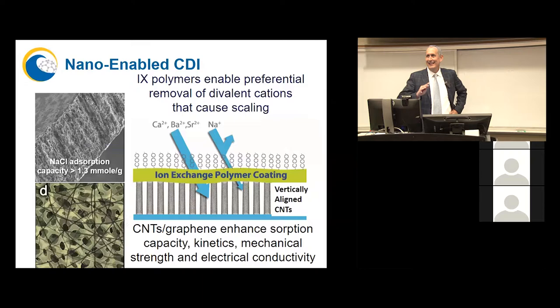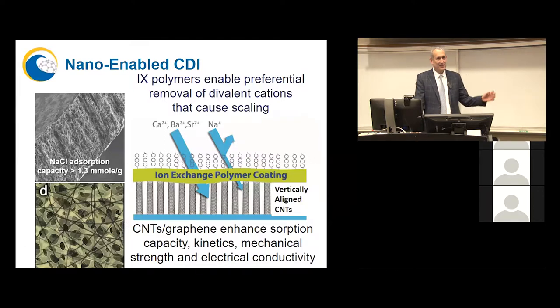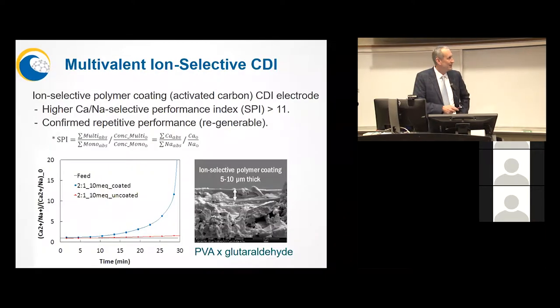The oil and gas industry doesn't care about removing common salt, sodium chloride, which is by far the most abundant ion present in this water. That's because their friction reducers and gelling agents work well with salt. What they want to remove are multivalent cations like calcium, barium, and strontium that cause scaling. So to make this selective for the removal of these compounds, we're trying to use ion exchange polymer coatings, very thin coatings, that exhibit high permselectivity for the target compounds. On a first trial, we were using a cross-linked polymer of PVA with glutaraldehyde. It's a thin layer coating activated carbon electrodes here that are relatively cheap, just 5 to 10 micrometers thickness.